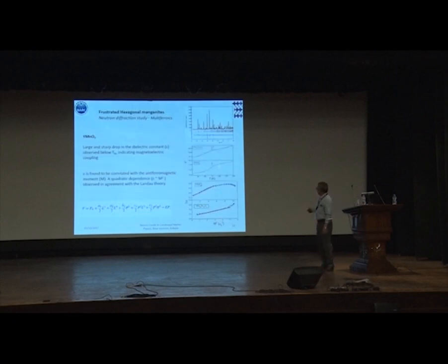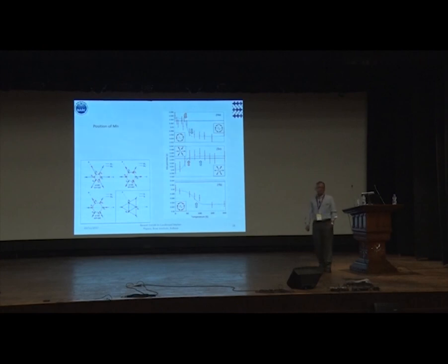The question was what is happening here — it is far away from the ferroelectric transition temperature and our own experiments did not give the clue. An experiment done at LLB, France revealed that the manganese position in the lattice actually changes at the transition temperature. The manganese position, roughly around 0.33, undergoes a slight change at T_N. So a displacement of manganese from its position is what is causing the magnetoelastic coupling at the transition temperature.